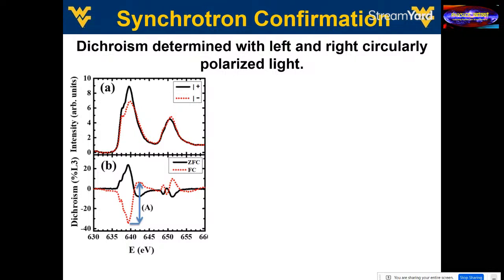So a lot of the concern in this field is, well, maybe this is some sort of weird artifact from your magnetization in your coils. So since we do a lot of different beamline measurements, it was pretty trivial for us to actually go and use a technique where we didn't even have to apply a magnetic field to the sample.